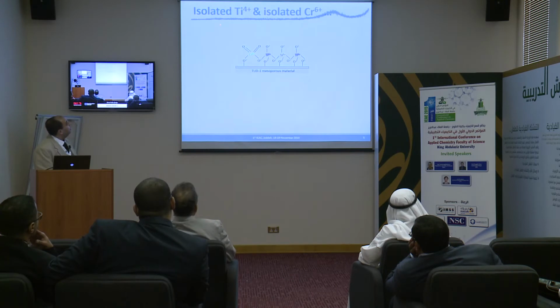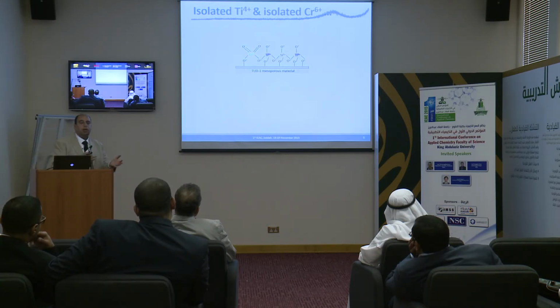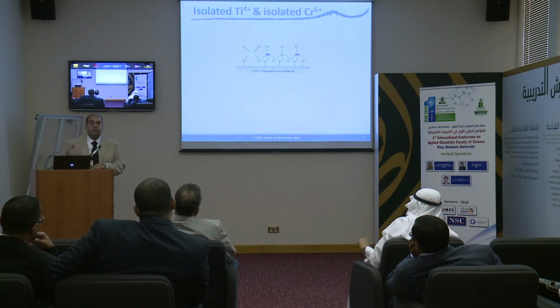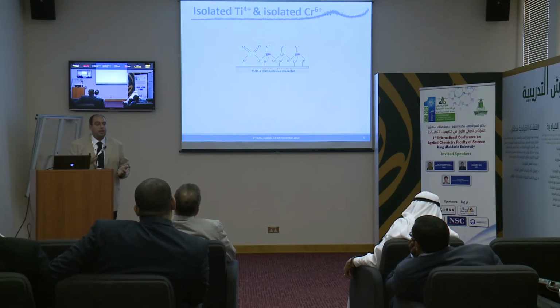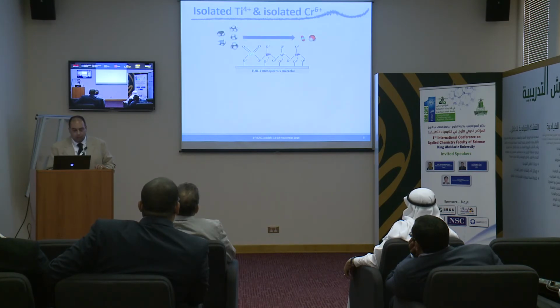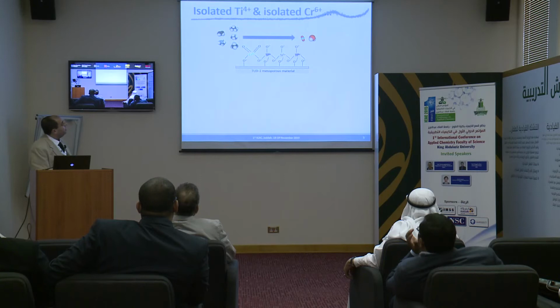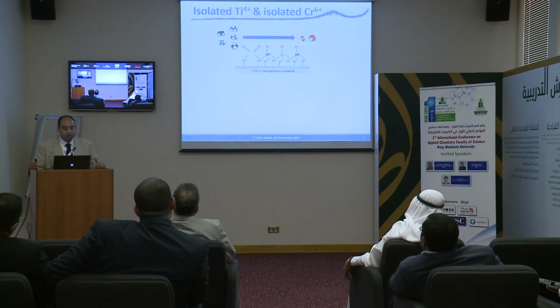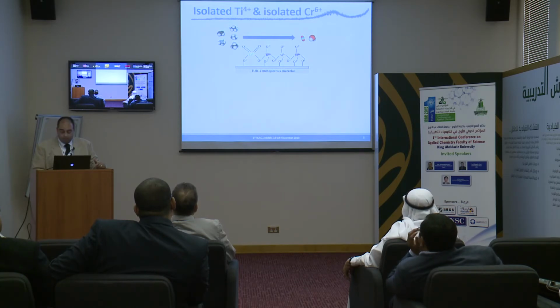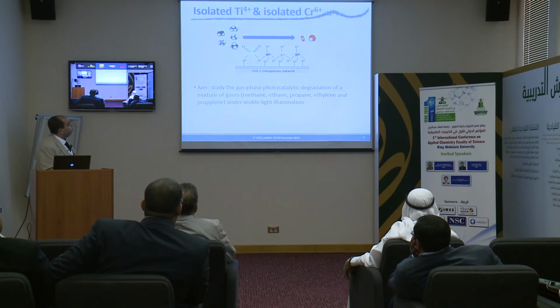Let's start with the first one. If you have isolated titanium and isolated hexavalent chromium ions supported on the TUD1, and actually this is a very old trick. People published a lot about shifting the absorption spectra of isolated titanium to work as a photocatalyst in the visible light region. And for the first time, actually, we applied the degradation of 5 different gases at the same time. So we applied methane, ethane, ethylene, propane, propylene, 25 ppm of each, to totally degrade these 5 gases to carbon dioxide and water.